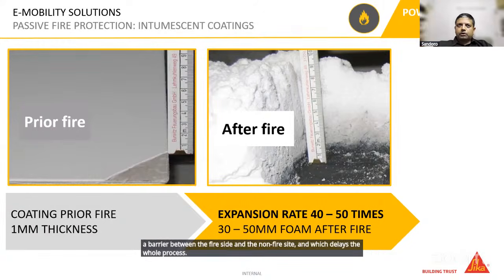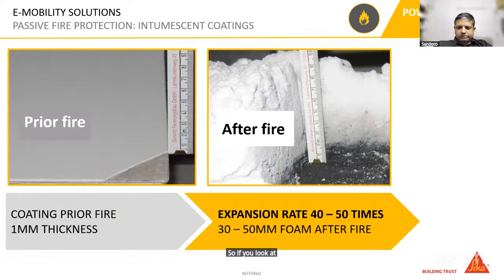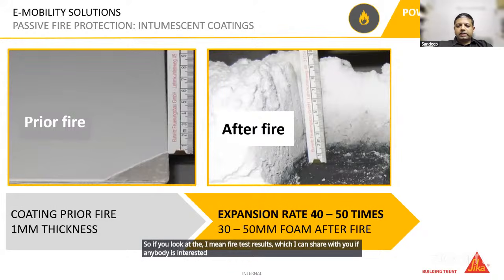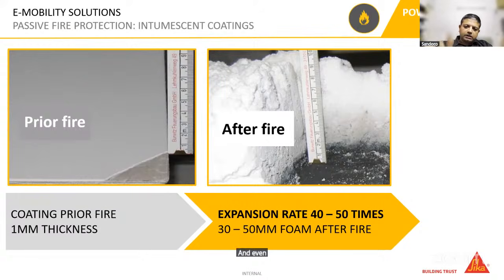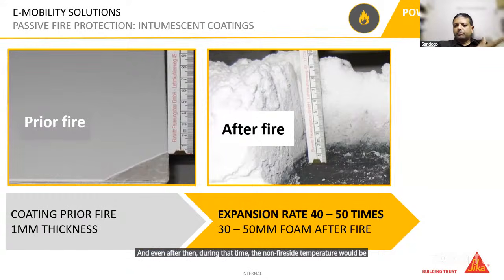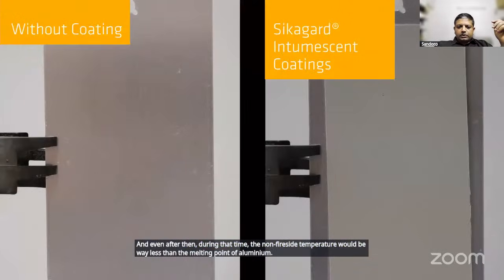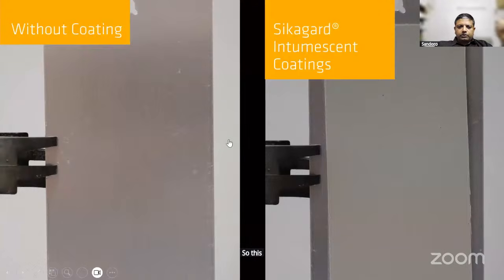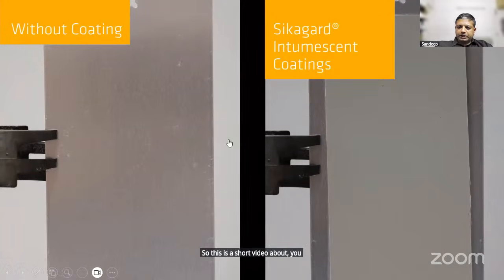If you look at the fire test results, which I can share with you if anybody is interested, there is a clear delta T of almost 400 to 500 degrees between the fire side and the non-fire side. And during thermal runaway, temperatures can go beyond 1,200 degrees Celsius. Even then, the non-fire side temperature would be way less than the melting point of aluminium. So this is a short video about how the material reacts during fire.